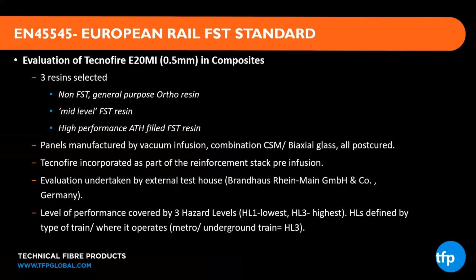So we wanted to assess the impact of incorporating a 0.5 millimeter layer of a Technofire incandescent veil, in this case E20 Mi, and the E20 expands by 20 times its original thickness when it's activated in the fire event. So we selected three different resin systems to assess in the composite application: a non-FST general purpose orthophthalic resin to start with. We then moved on to a mid-level FST resin, and then finally a high performance, heavily ATH filled FST resin. And panels were manufactured by vacuum infusion using a typical combination chop strand matte biax glass, and all the panels were post-cured.